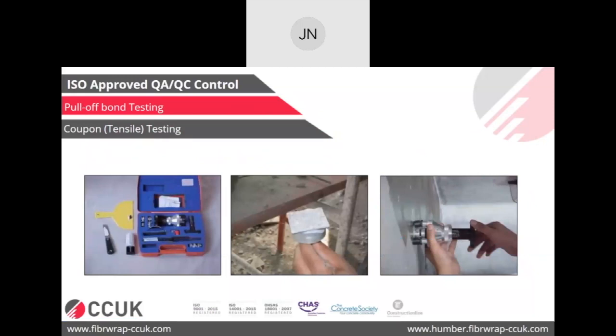We'll see some quality control tests and checks which you do after application of FRP. So generally FRP is tested for 2 types of failures. So one is debonding and delamination, which happens especially in the bond critical application if the fabric is dry or if the application is not done properly. So for that test, what you do is a normal pull-off test. So on every strengthening you do, you put a sacrificial patch next to it so it cures in the same environment and everything. And after the 100% curing of FRP, you go and do a pull-off test.